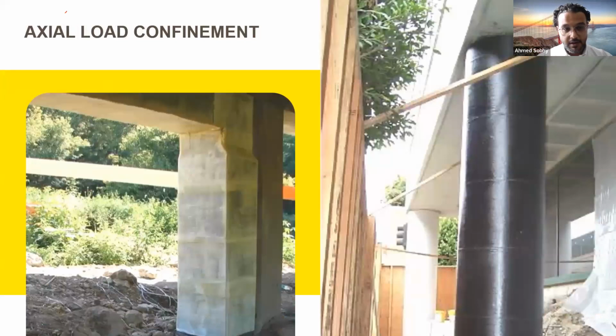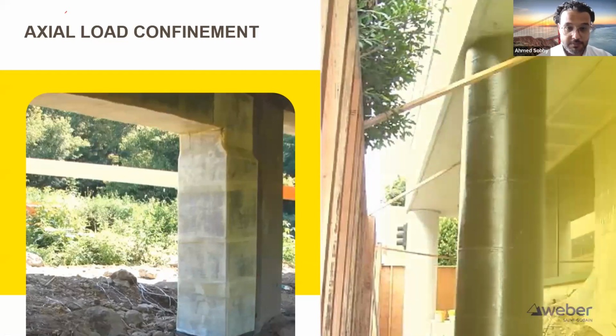In this application here, obviously it was used for axial load confinement. And what's interesting about this application is that there are two columns with a very, very minimal space between the two of them. Because of the very small thickness of the material, the design here opted for structural strengthening of one column rather than two. Again, because of this very small thickness, it was able to be extended between the minimum thickness between the two columns. If another system was to be specified and used, it would have definitely included the two columns together rather than one, because of the very minimum thickness that you see between the two columns.